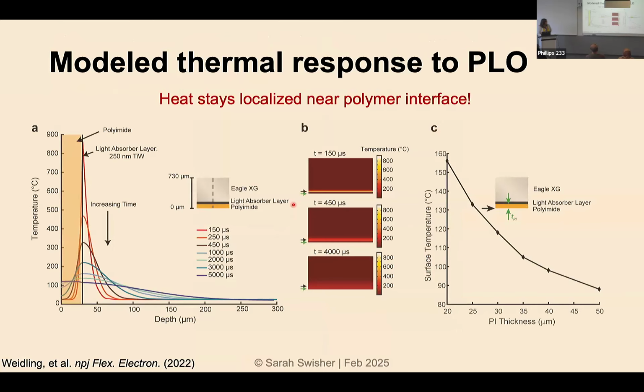And when we model this, again, using a similar COMSOL model that we had used before, what we see is that the heat really does stay localized at this interface. So this yellow is the polyimide, and the heat is really localized here at the interface. So this is as a function of time. You can see that with increasing time, this heat dissipates very quickly. This is 5,000 microseconds here.